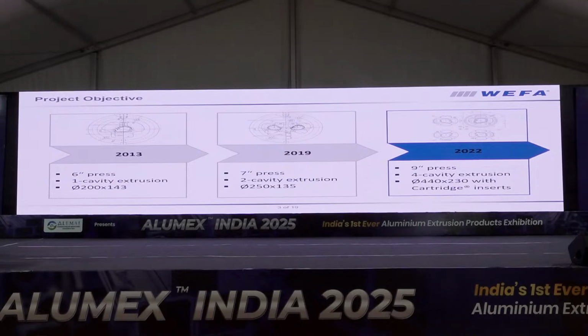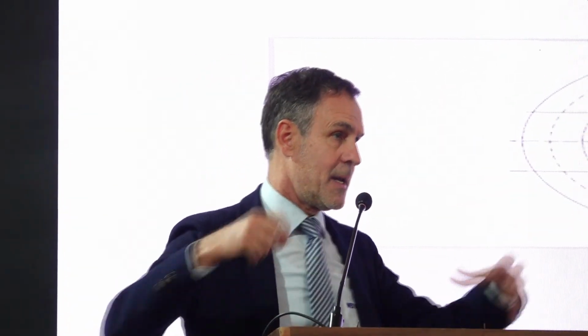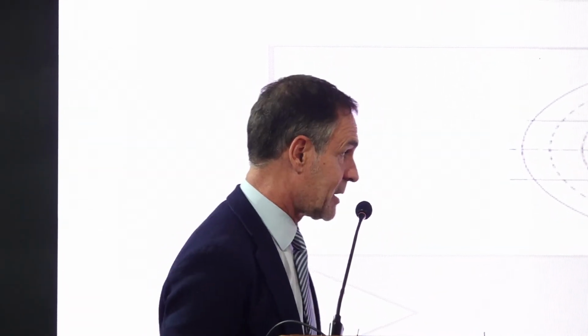It's a 9-inch press, and here we also try to incorporate 4 little cartridges. Usually you have a big die, and there we try to use individual units, inserts, so-called cartridges. That was the productivity increase we tried to achieve from 2019 to 2022 by doubling the number of strands. And that's not the only one. We also tried to use coated cartridge inserts, which I show you here.